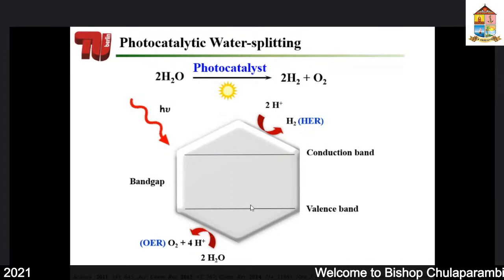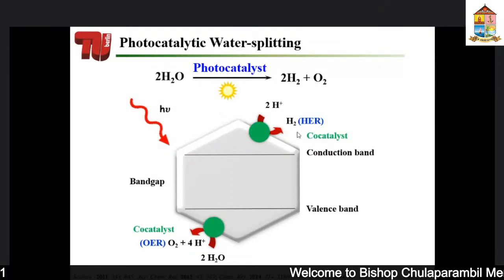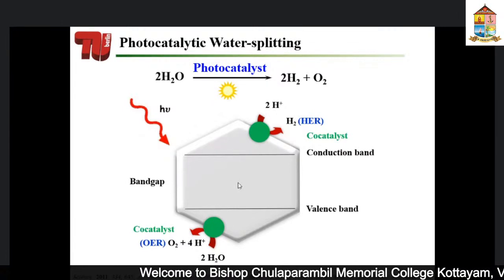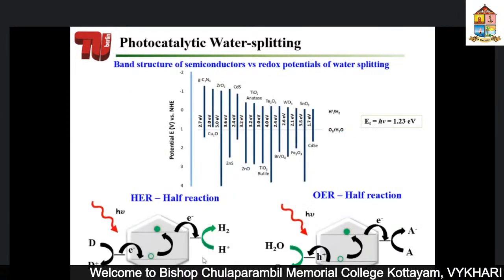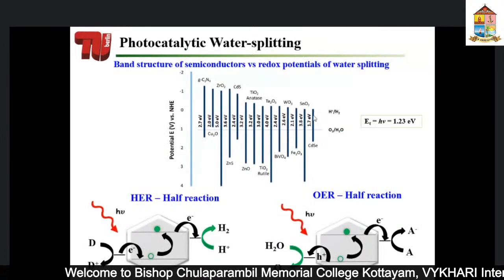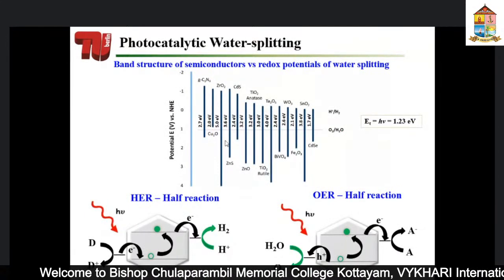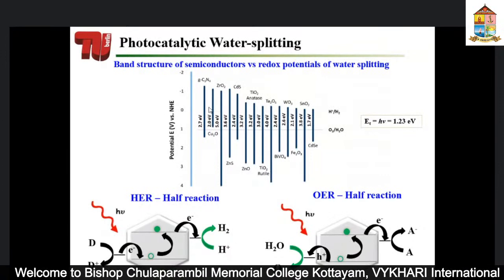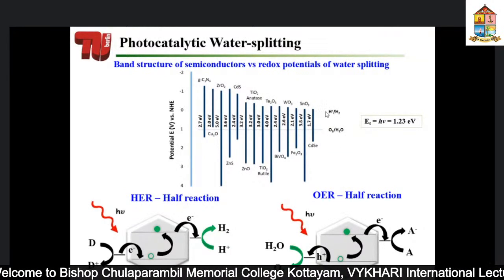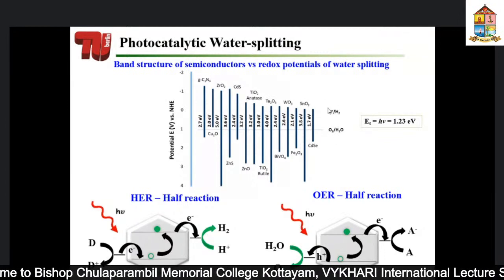Therefore, what could be done? One could use something like a co-catalyst, which can trap the electron the moment it goes to the conduction band, and then produce hydrogen at one end, while at the other end it can take out the hole and somehow make this oxygen evolution feasible, so that we don't have any recombination. Now the question is, does such a catalyst exist? You can see the band structure of the semiconductors. This is the band gap. What you see here is that most of the materials do not have a suitable band gap to oxidize water or reduce protons at the same time.